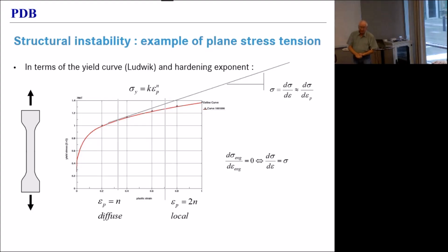the yield strength. And if you then throw a very, very simple equation at the yield curve, like the Ludwik equation, yield stress is equal to K equivalent plastic strain to the power of N, and you do two lines of algebra, you find that the diffuse necking starts for an equivalent plastic strain equal to N, N being the hardening exponent. Now, with an additional two more lines of algebra, you find that local necking starts at 2N. So it's quite far away.